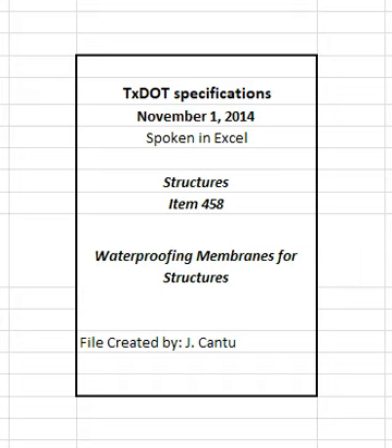The minimum ambient temperature at the time of waterproofing application is 40 degrees Fahrenheit. Do not begin backfilling until the second coat of waterproofing has cured sufficiently to prevent damage by the backfilling operation. 3.7 Type 6. Apply the primer at a rate of 1 gallons per 100 square feet of surface or at the rate recommended by the manufacturer if different. Allow to dry to a tacky surface before placing the waterproofing membrane.